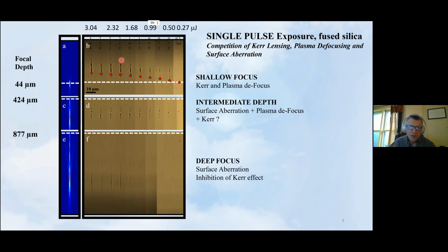But if we go shallow, there's a very tight focus, the intensities are higher, and you see this Kerr effect. The beam is actually focusing, misaligning, focusing higher. And at intermediate depths, you're seeing both a self-focusing and a defocusing effect due to plasma distortions, plus the effect of aberration shift in the beam below the focus. So really, even just getting the light into the material is a game of trying to understand how much energy you can apply and whether you are going to get the shapes you like.